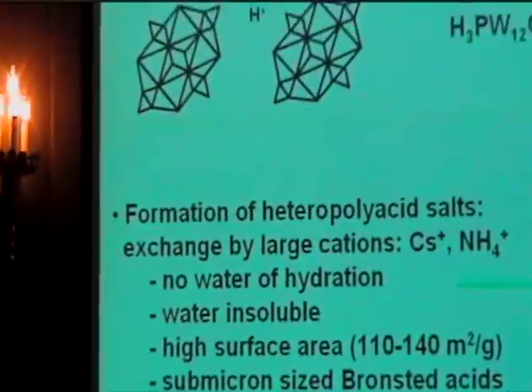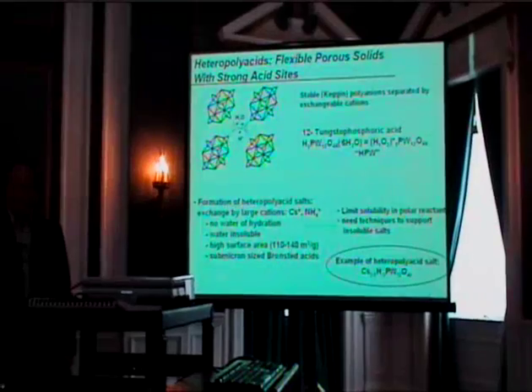Because the interesting thing about these materials as opposed to zeolites is that you can replace 70 or 80% or even more of the protons here with a basic cesium. Yet there's enough shielding from these anions that the few protons that are left still have a lot of acidity associated with them. If you do the same thing for zeolite, you put that much cesium in there, the zeolite is done.